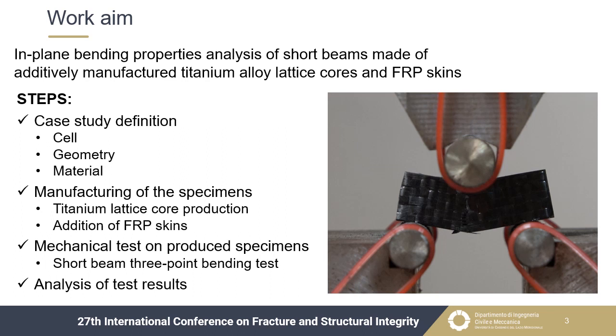Then, the specimens were produced according to a two-step process. In the first one, the cores were manufactured through the EBM process. Then, the skins were added by curing the prepreg layers on the cores. After, the produced specimens were tested, and the obtained results were presented and discussed.